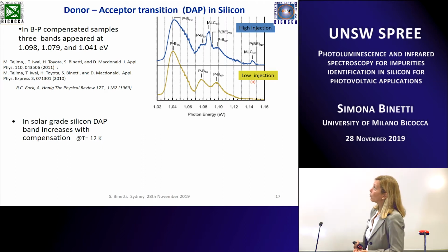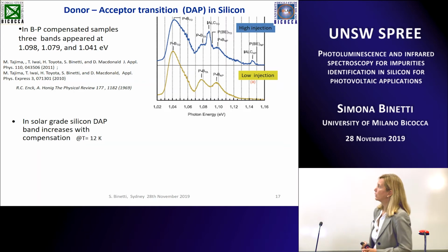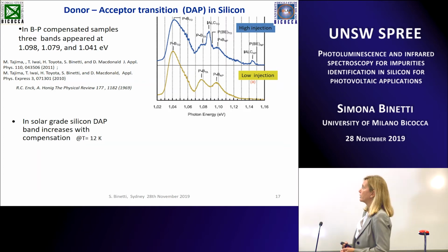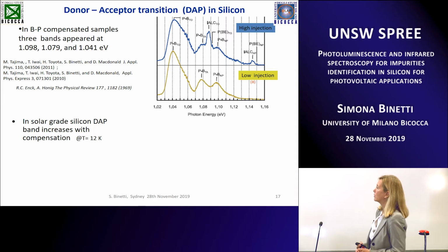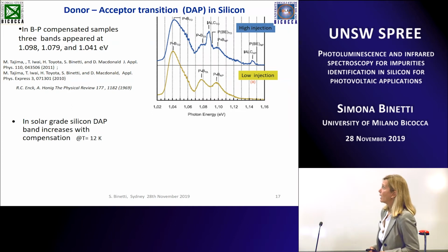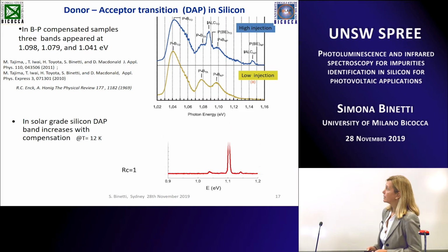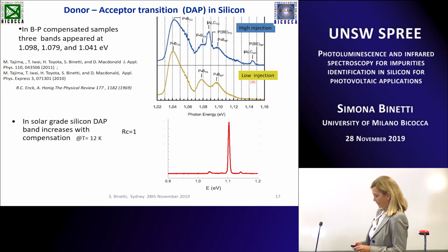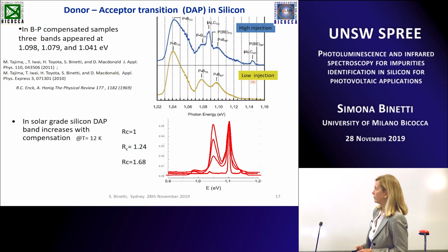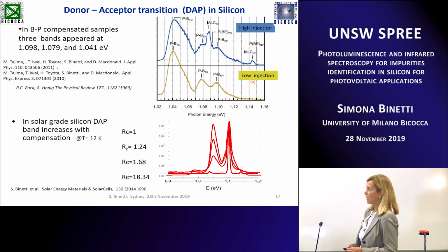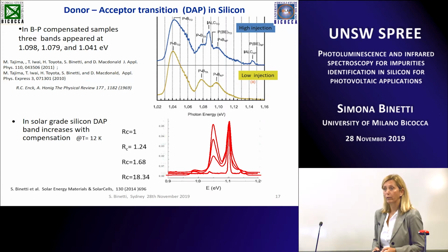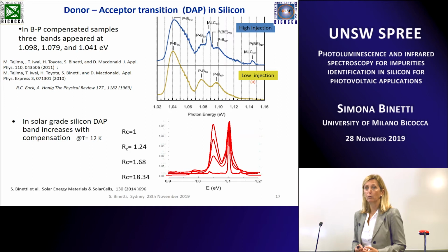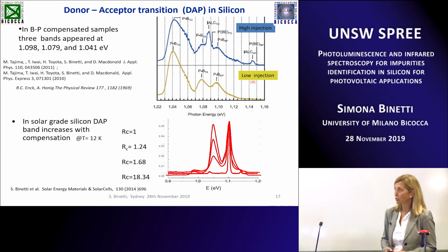And in a quite recent work that we have carried out in collaboration with Tajima and also with D. Macdonald of ANU, Australian National University in Canberra, we studied the donor-acceptor transition in boron-phosphorus compensated silicon. And we detected the band, and also we have seen that in solar grade silicon you can have this band, and this band increases with the compensation ratio, so it can be used as a fingerprint of the compensation in your material, and also you can use this band to check the compensation ratio of this material.